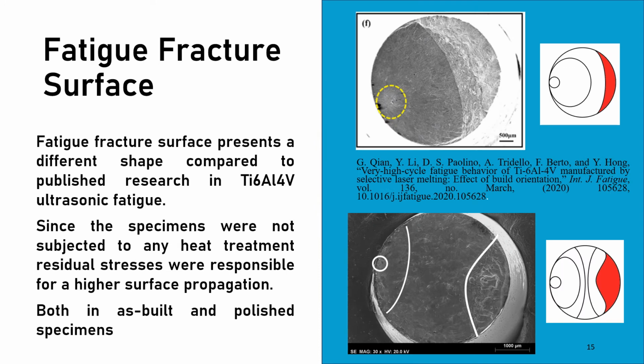Now, there's an important conclusion to take when observing the fatigue fracture surface overall and comparing it to previously published results in the same titanium with the SLM AM method. If we take a look at the published results in SLM titanium tested at ultrasonic frequencies, there's a continuous propagation following the same curvature until the total failure of the specimen.